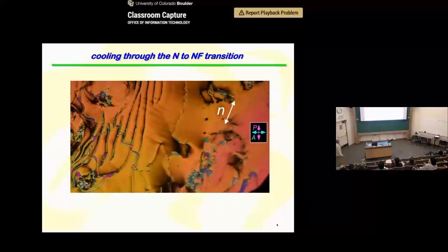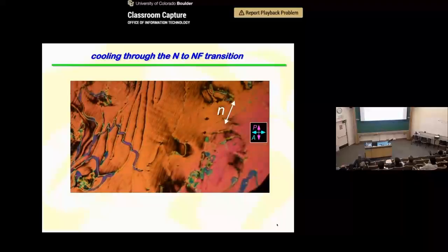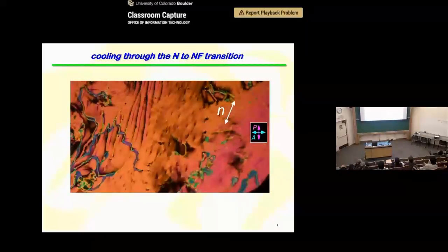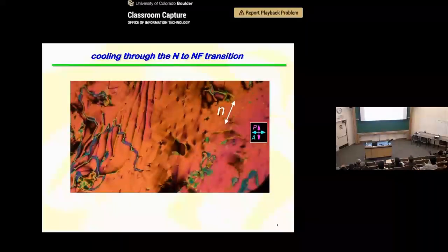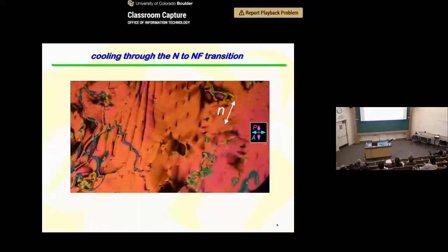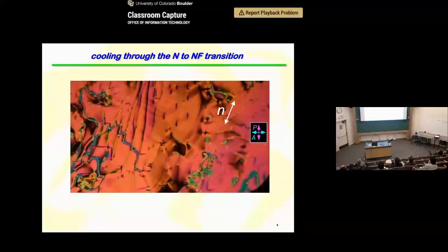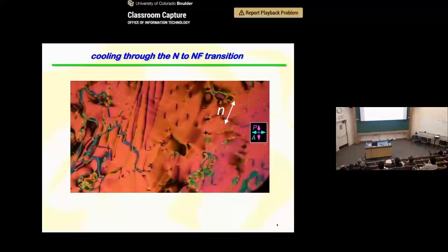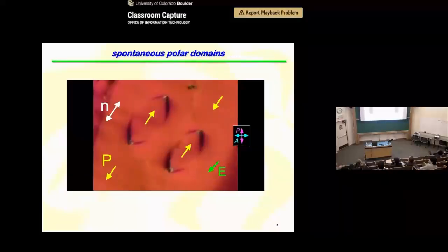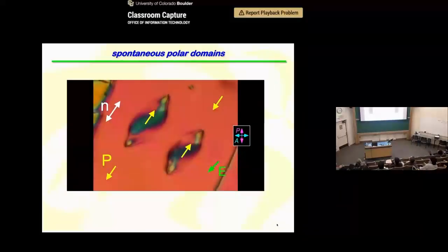Yeah, here it goes. So you see these striations appear along the average orientation direction, which is the white arrow. They coarsen, they turn into a series of lines, and then these lines organize themselves, and now we're in the ferroelectric phase. And so I'll be interested in this region here where the lines have formed loops, okay? So here are the loops.